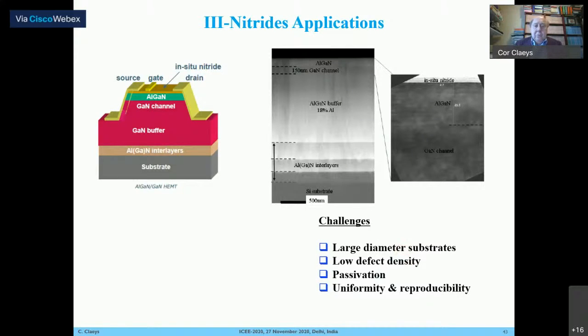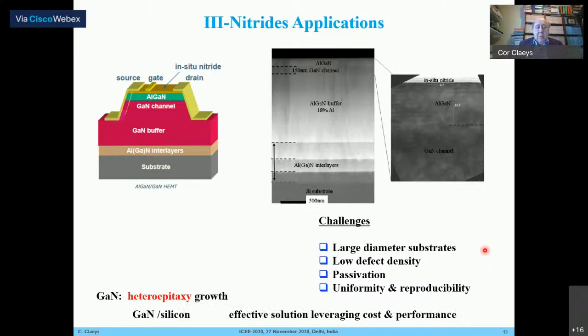But as already mentioned, in order to grow gallium nitride on silicon, you also need the appropriate buffer layers. That means you have to work again on defect control. And similar as for other III-V materials, you have to optimize the gate dielectric. You have to work with passivation layers in order to get a very good interface quality. And you have to work on the uniformity and the reproducibility. However, we can say that heteroepitaxy of gallium nitride on silicon is a very effective solution from a viewpoint of cost and performance. And if you want to make gallium nitride devices, there are different approaches.